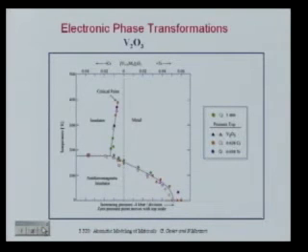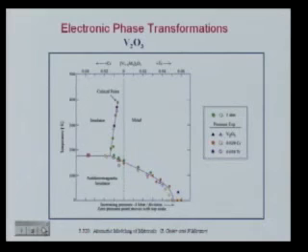And here's the ultimate one. I thought that this didn't exist. For a long time, us alloy theorists have wiped away electronic entropy because we just don't know how to deal with it, and we don't like to deal with it. So we write in papers saying that it's not important. But here's a system that's completely driven by electronic entropy. Now, agreed, it's slightly esoteric. It's vanadium oxide, which undergoes metal insulator transitions. This is its phase diagram in temperature pressure space, since there's no compositional axis. It's a stoichiometric compound. And at low temperature and low pressure, it's an antiferromagnetic insulator. If you raise the temperature, it becomes metallic and changes structure.